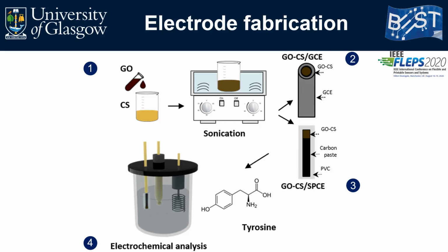The graphene oxide Chitosan modified glassy carbon electrode, or the modified screen-printed carbon electrode, were then coupled with a silver-silver chloride reference electrode and a platinum wire counter electrode for the electrochemical detection of tyrosine using an electrochemical workstation.